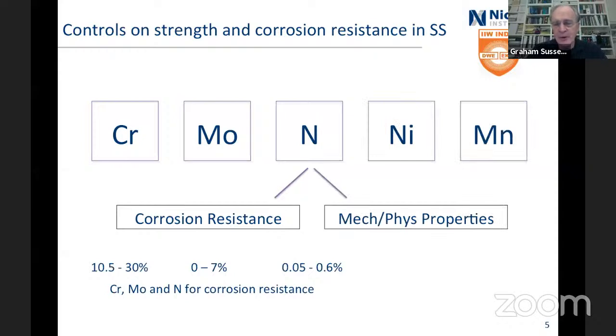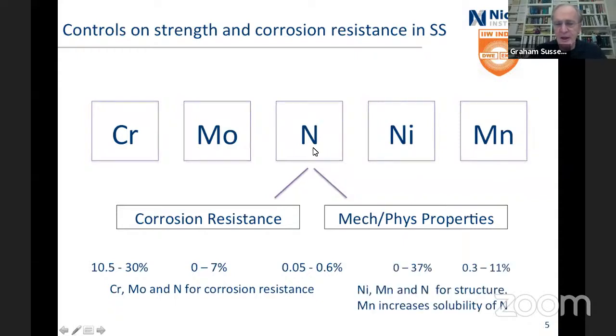Then you've got the mechanical properties, and the things that control that are the nickel, the manganese, and again, the nitrogen. And the amount of material, well, nickel can go up to 37%, although it doesn't do anything like that in the duplex stainless steels. Manganese up to about 11%, although most of the duplexes don't have as much as that, they have a lot less. But this nitrogen bit is really quite important, and it is of critical importance to making sure that the duplex stainless steels work.